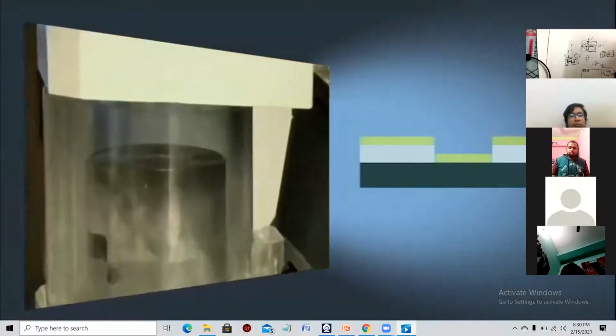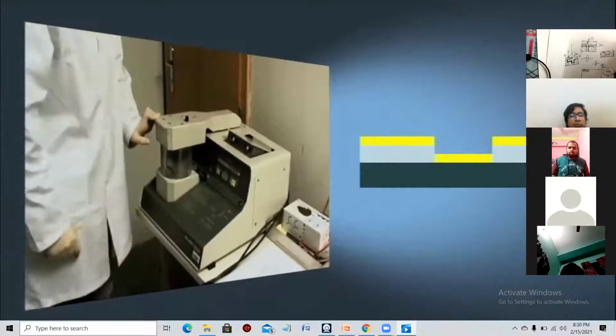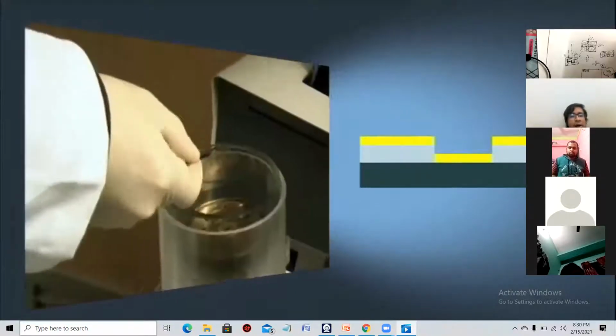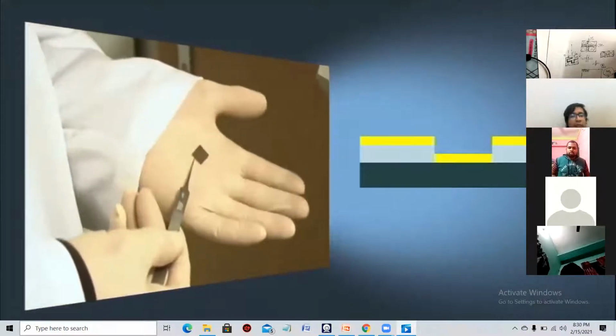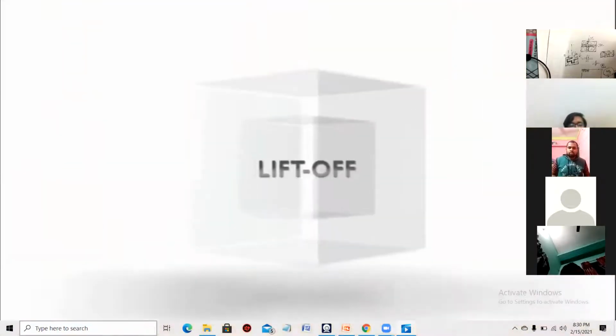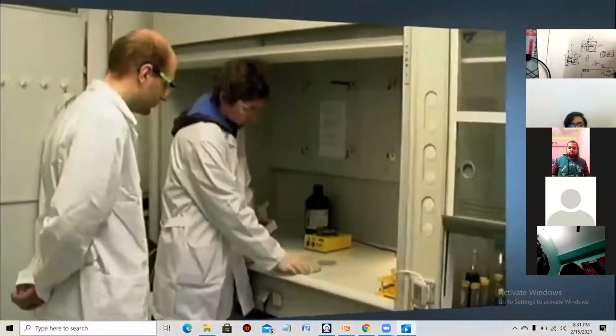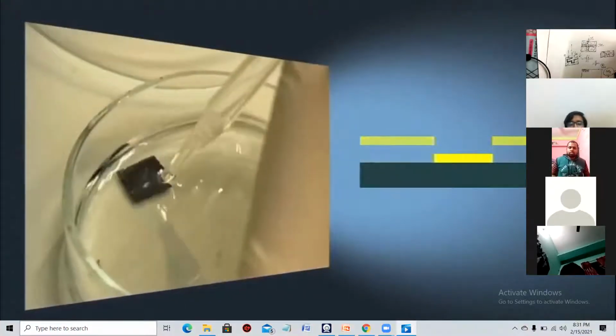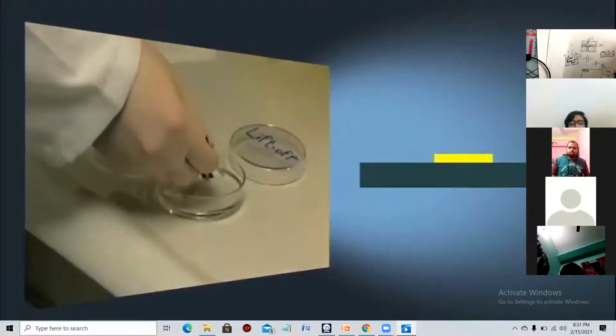On the parts where the circuit was drawn and the film dissolved, the metal can stick directly to the silicon, while everywhere else there is still a polymer film between the metal and the wafer. The final step is removing all of the remaining polymer together with the unwanted metal. The wafer is put into a different solvent which dissolves the polymer. The metal on the polymer also floats off, while the metal that is directly on the silicon wafer stays intact. And the result are two very small and precise electrodes.